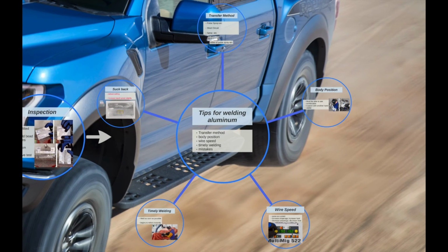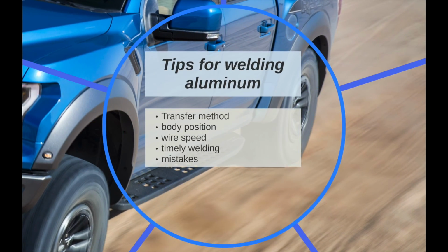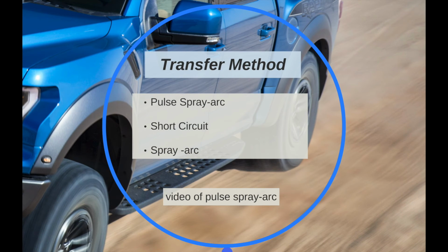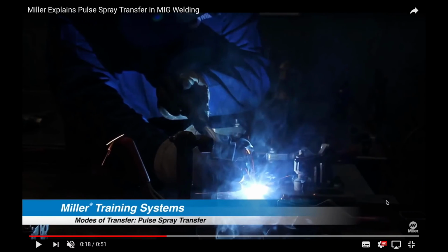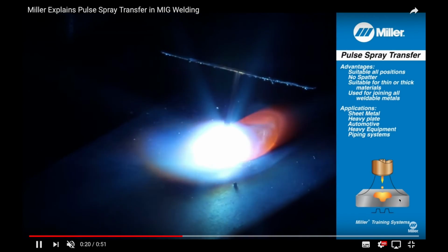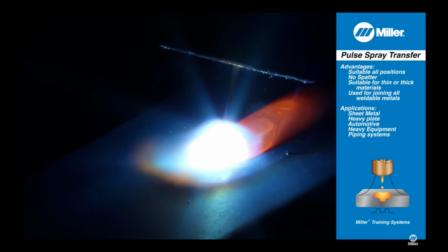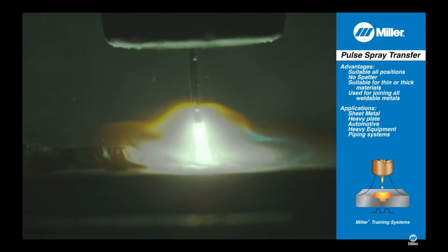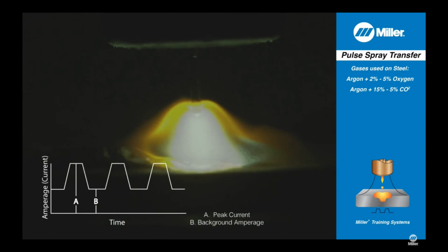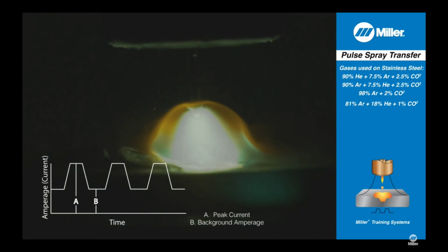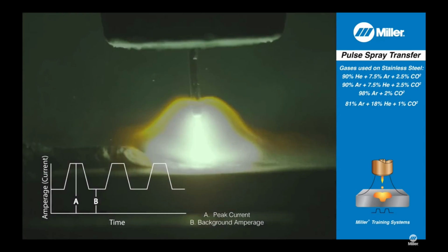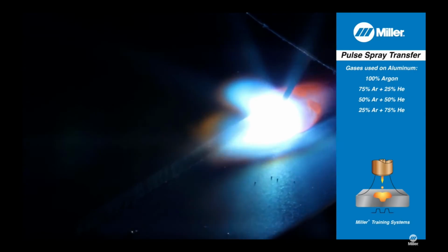After all the techniques, there are also a few tips for welding aluminum. First one, there are 3 transfer methods recommended for aluminum: pulse, spray arc, and short circuit. Personally, I think pulse spray arc is the best transfer method for aluminum, due to my experience. Here is a video explaining what the pulse spray arc transfer method is. Pulse spray transfer sprays a stream of tiny molten droplets across the arc from the electrode to the base metal. But unlike spray transfer, the stream is not continuous. The power source rapidly pulses the welding output between high peak currents that cause the transfer to spray and a lower background current that maintains the arc but does not allow any metal transfer to occur. The pulsing of the current produces a buzzing sound.